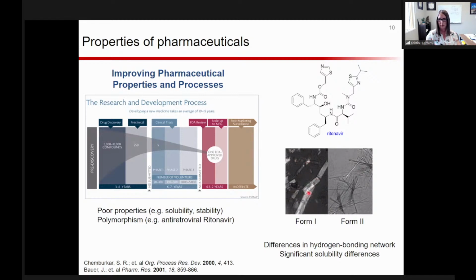You can see the crystals are relatively blocky looking. But after ritonavir had been on the market for a period of time, they were synthesizing it in the lab, and a second polymorph appeared. These crystals are very needle-like instead of the blocky forms. The difference in those two forms is how ritonavir hydrogen bonds with itself. It hydrogen bonds in two different fashions in form 1 and form 2.